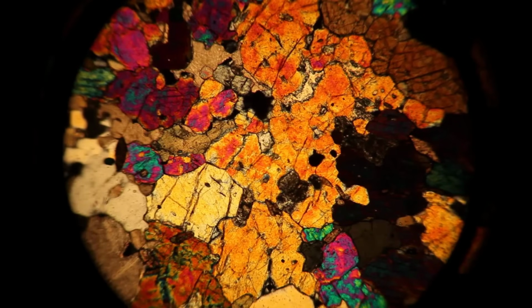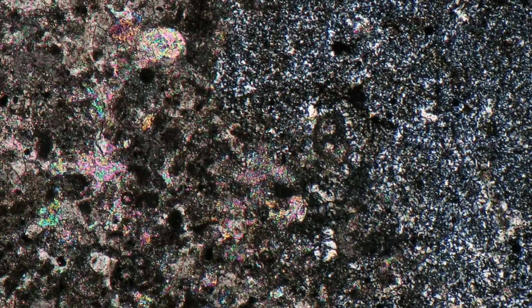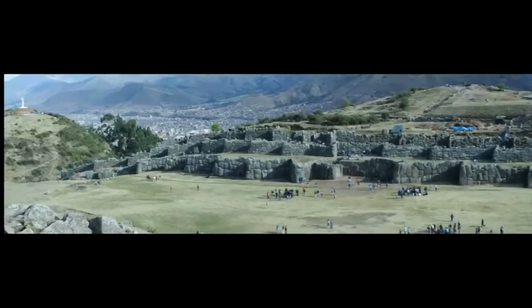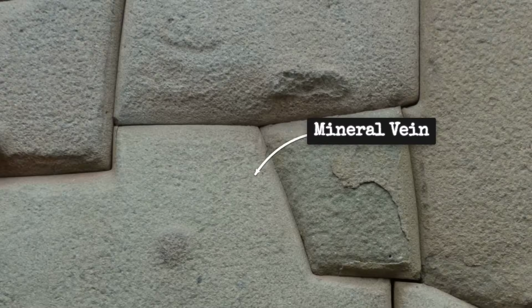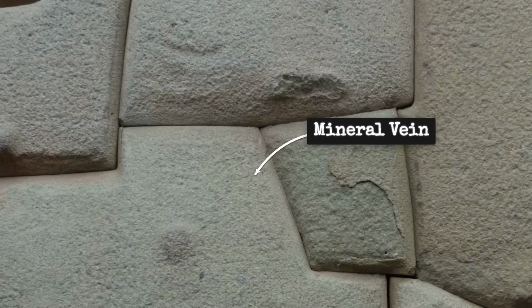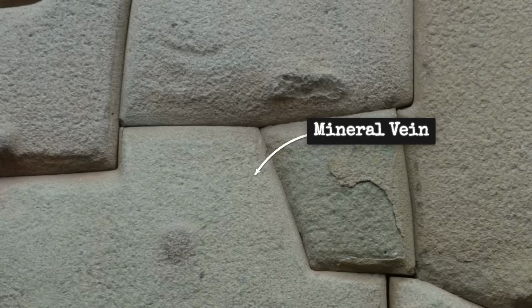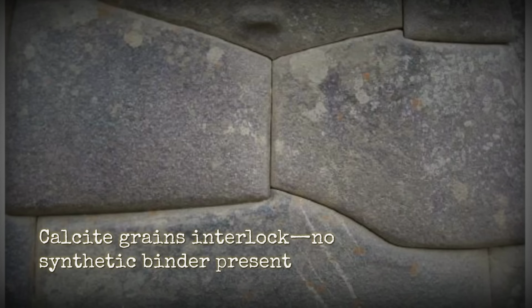Yet, sample after sample returns the same verdict. The limestone is dense, microcrystalline, and nearly identical to the raw blocks still exposed on the hillside above the fortress. Natural mineral veins cut through both the so-called shell and core of the basal stones, threading across boundaries that would have been sharp if poured in separate phases.